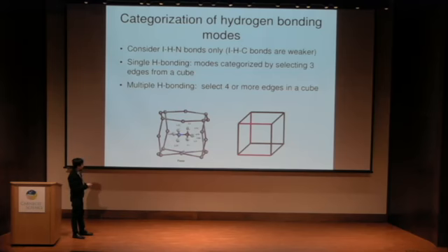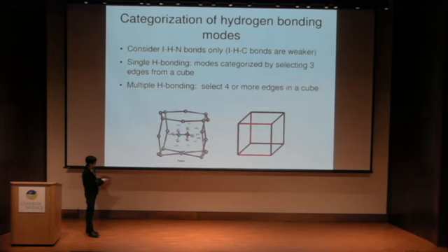Now, if you look at a single hydrogen bond, most of the time, one hydrogen bonds to one iodine, in the sense that if you collate all the distances of the hydrogen bonds, there's one which is very much shorter than the rest. But there are some cases where there are multiple hydrogen bonds very close in distance to each other, like this one, for example. There's 3.52 angstroms here and another 3.5 angstroms. So in some cases, there are multiple bonds. So how do I handle this?